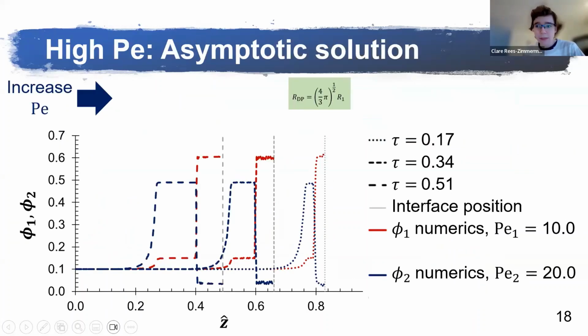On this slide, I have some results for higher Peclet number. That is a fast evaporation compared to diffusion. You'll now see that at the right-hand side of the graph, the red line is much higher than the blue line. So it's predicting a strong small-on-top stratification, suggesting that fast evaporation could be a way to obtain this strong stratification.